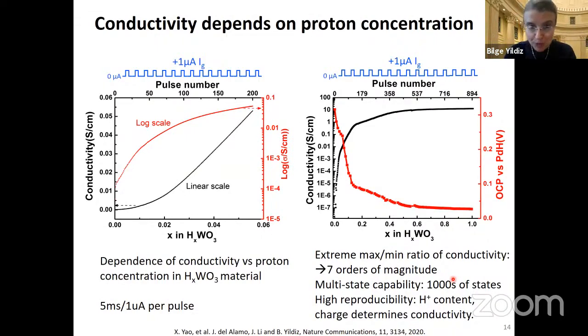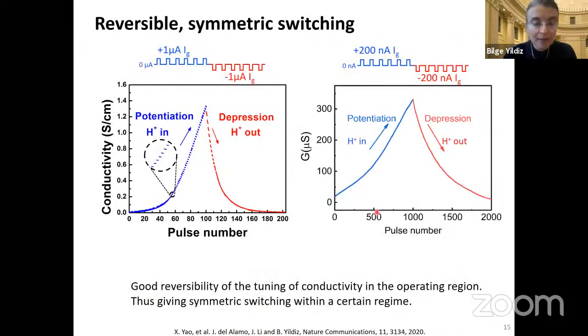And is it reproducible, reversible? That's also very important. And we can see that indeed we can obtain this potentiation and depression in a quite symmetric fashion, which is important again for use of this in reliable training of physical neural networks. And let's look at both of these curves. They are just in different ranges of protonation. As we send protons with positive potential into tungsten oxide, we increase its conductivity. And this is exactly what I have shown to you in the biological synapse as the potentiation behavior.